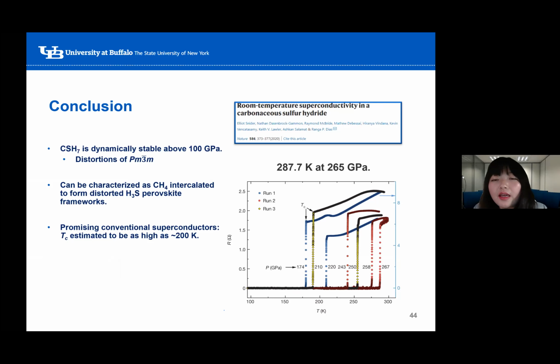Recently, Professor Dias and his team published experimental measurements for the CSH system at high pressure and found the highest Tc to be 287 Kelvin at 265 GPa. So this phase has not been identified yet. We believe that would be a good motivation for a future project.